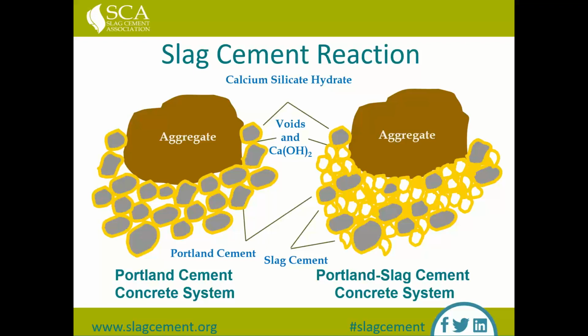As you're looking at this, the gray represents your cement particles. The yellowish tannish material is calcium silicate hydrate, or CSH. This CSH is the primary product from Portland cement and water hydration, and it's also the glue responsible for the strength. The white areas in between are voids, and there is some calcium hydroxide or free lime in those areas.